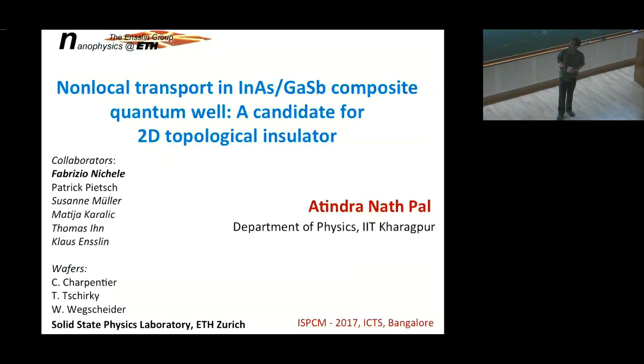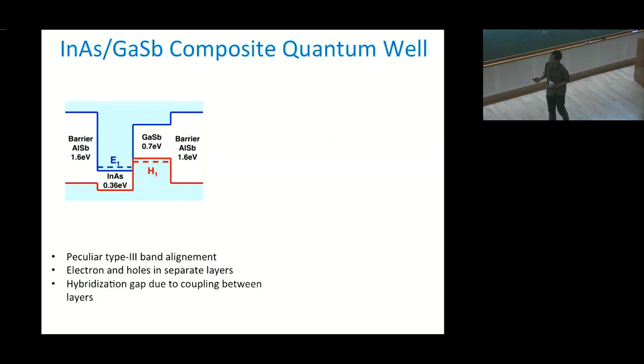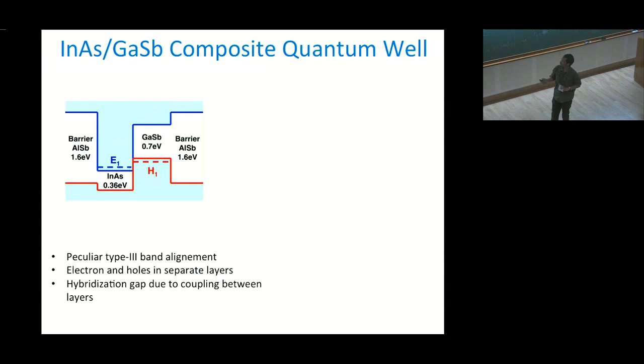This is a possible candidate for a two-dimensional topological insulator. The system is as follows: we sandwich two materials — one thin layer of indium arsenide and one thin layer of gallium antimonide. Both are narrow bandgap semiconductors. Indium arsenide has a bandgap of 0.36 eV, gallium antimonide has 0.7 eV. These are sandwiched between two barrier materials, aluminum antimonide, which has a bandgap of 1.6 eV.